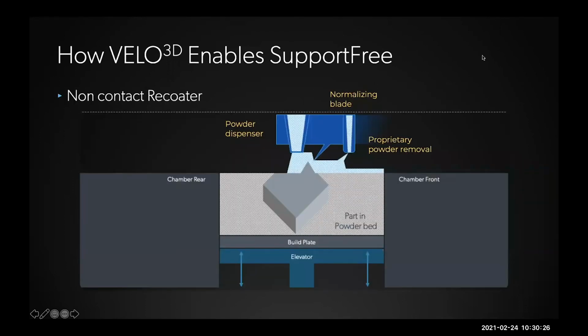So here's our claim to fame, really: our non-contact recoater. This is how it all started with Velo 3D. This is not a dump and smear recoater system. It does dispense a thick layer of powder in the recoating motion. Then right behind that powder dispenser, there's a normalizing blade. This blade flattens and levels out the dispensed surface such that it is then approached by our proprietary powder removal tool that removes all but 50 microns of powder. So we have a nominal layer thickness every layer.